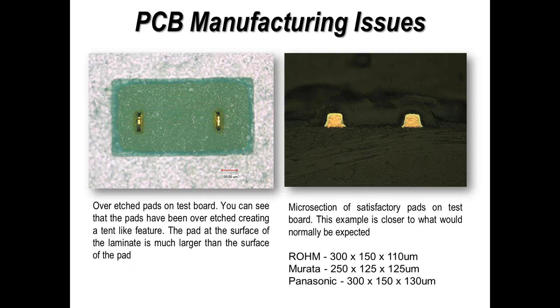And if you look at the slide here on the left-hand side, you can see that the actual pads have been quite over-etched. They've actually got a point rather than a flat surface we're actually printing onto. So in this particular case, it did give us some problems during the printing process. On the right-hand side, the microsection shows what you might expect with pads that have been correctly etched. And here you've got copper pads with nickel over the top surface. There is a slight chamfer edge to the pads, but again, this is normal when going through the etching and plating process, but certainly not as bad as you see on the left hand side.